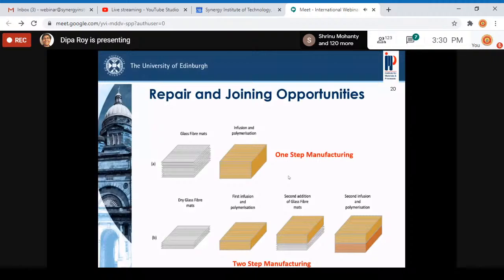We manufactured equivalent laminates, but one laminate we manufactured in one step, where we took 8 layers of glass fiber and infused the liquid resin. Then the resin polymerized in situ and we got the consolidated laminate. And we manufactured the same laminate in 2 steps. First we took 4 layers and infused them with liquid resin. Then it was polymerized, and we used that polymerized laminate with 4 dry glass fabrics, and then again infused the resin. So in the second step, the whole laminate was consolidated together.